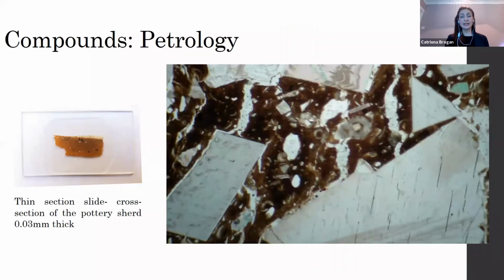So basically, to take you through the different techniques that we involved, I'll cover the ones that give us compounds, or in this case minerals, first. So the core of our fabric characterization is based on the petrology analysis, and this was actually conducted by Claudio Capelli at the University of Genoa. And for this, you use thin section slides of the pottery. So what we have here is a very, very thin sliver of pottery, and it's actually 0.03 millimeters thick. So this is really very fine and allows the light to pass through it.